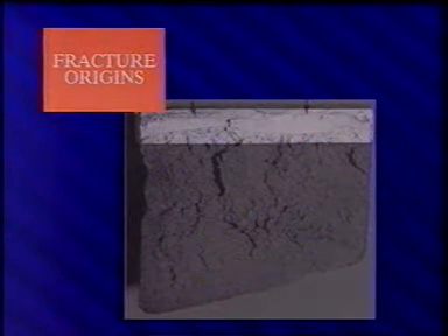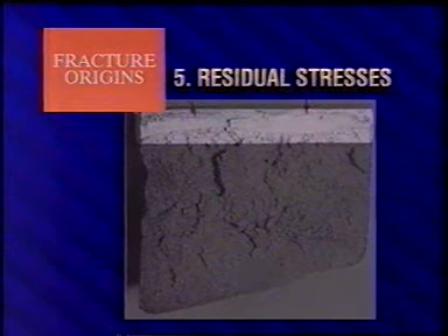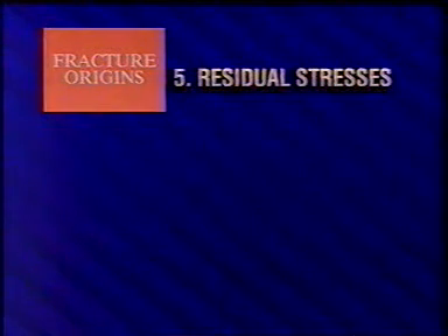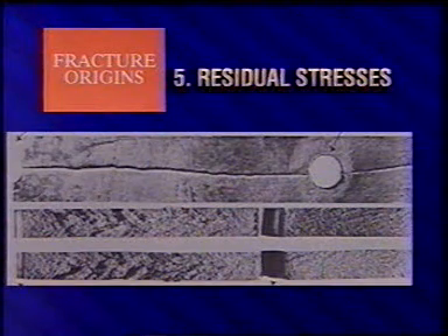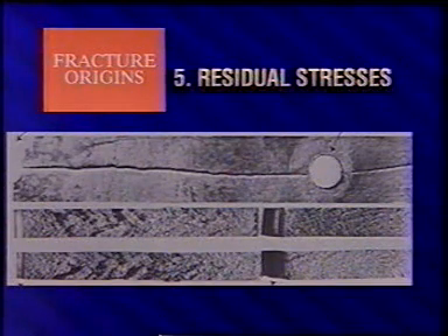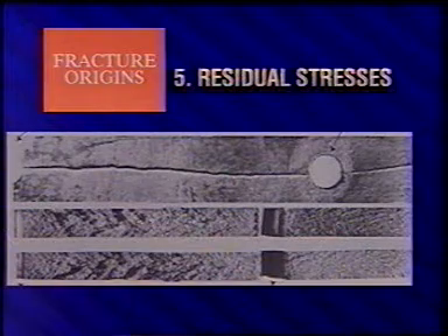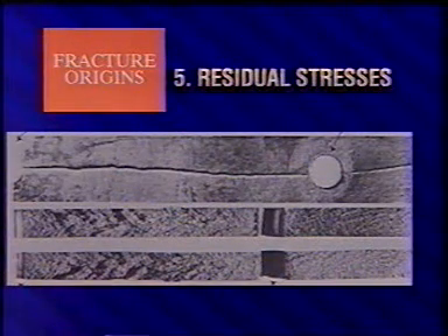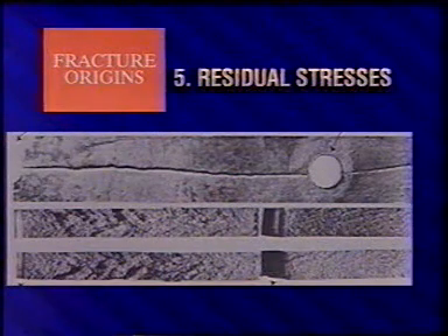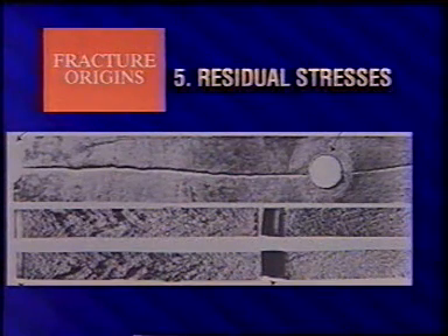Finally, residual stresses. Residual stresses are not defects in a geometric sense, but they can be an important factor in the initiation of brittle fractures. Here is a brittle fracture that originated from residual stresses at a hole punched in a steel plate. The chevron pattern is evident on the mating halves of the fracture, pointing back toward the hole. In such situations, moisture may have had access to the hole and contributed to the formation of the initial crack. Residual stress effects are most important in hard, strong metals. Softer, weaker metals can deform and relieve the residual stresses.